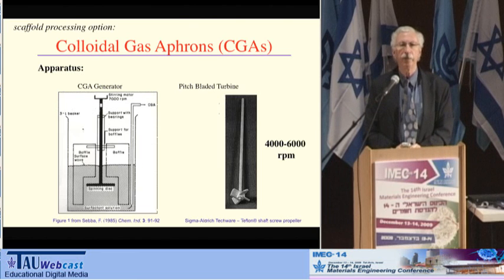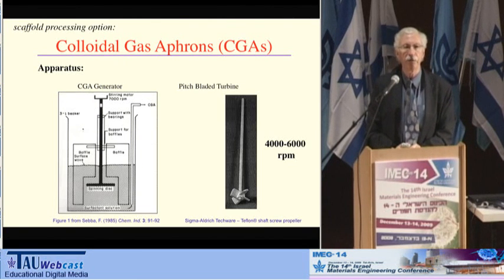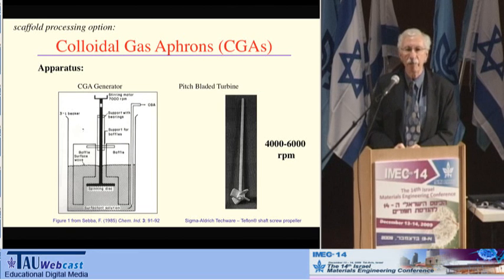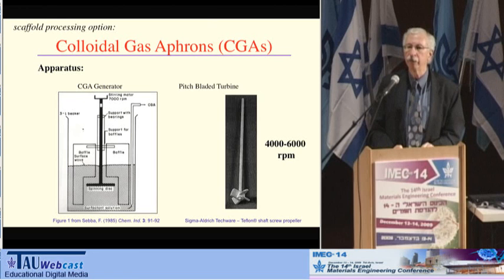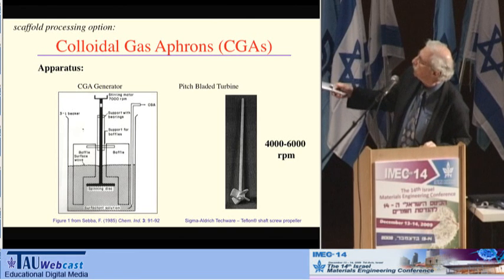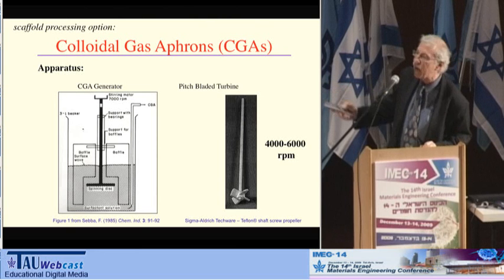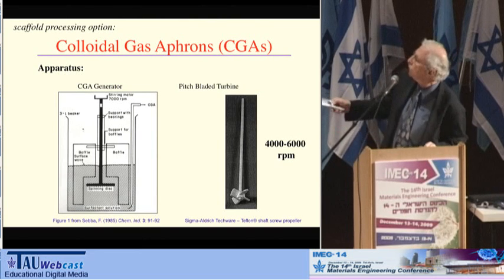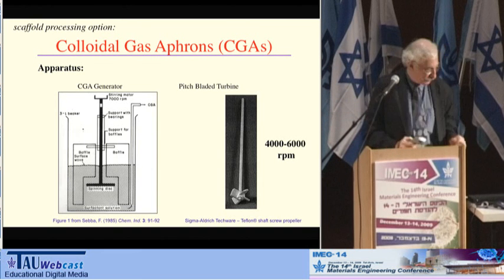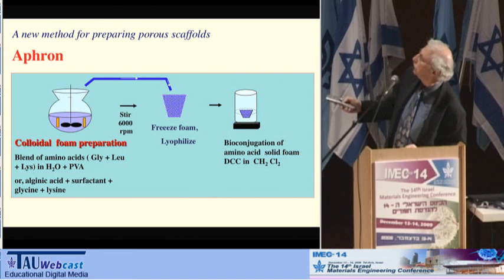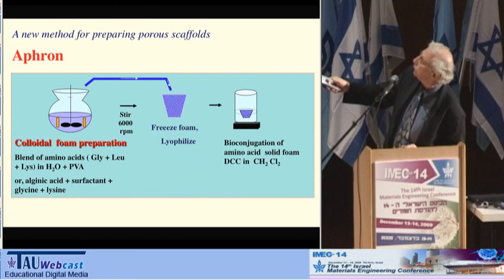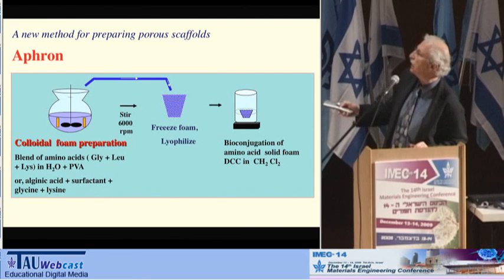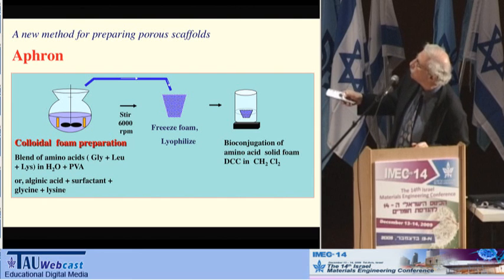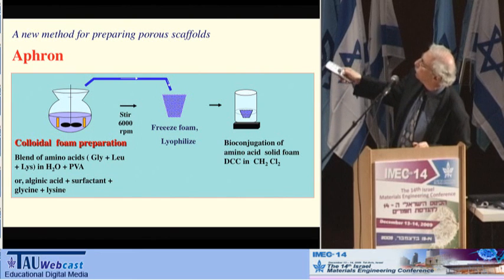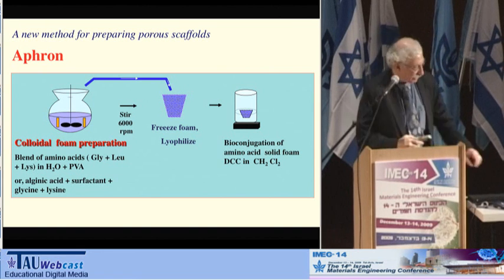Aphrons, the term comes actually from the chemical engineering literature, and what they really are, I sometimes think of them as a very fancy cappuccino. It's an ultrafine foam. Typically, one uses a stirrer with a specially designed baffle that distributes the shear force within the liquid and gives a very nice foaming. And again, in this example here, we have our stirrer and our baffles. I'm not going to go into the details of the scaffold. But we're going to make some foam, we're going to freeze it and lyophilize it, freeze dry it, and maybe conjugate some other things and make a scaffold out of it.